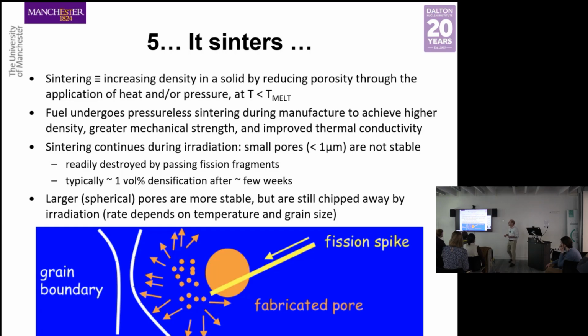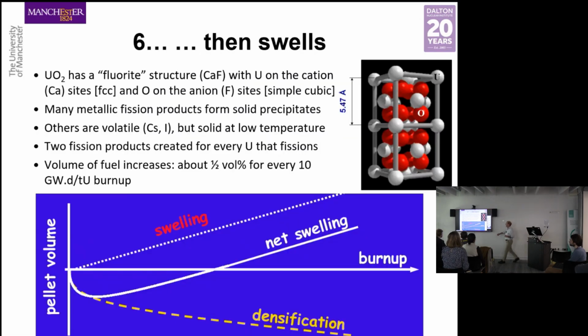We deliberately don't make the fuel 100% dense to begin with. We leave about 5% of porosity in the fuel pellet, and that provides a place for some of those fission products to actually go. Provides little reservoirs where the fission gas can be accommodated inside the fuel. But the problem is, as soon as we put the fuel into the reactor, that 5% becomes 4.5, and then 4, and then 3.5, and it just continues, and eventually that densification levels out.